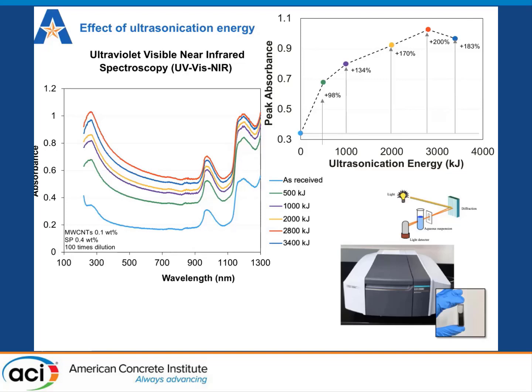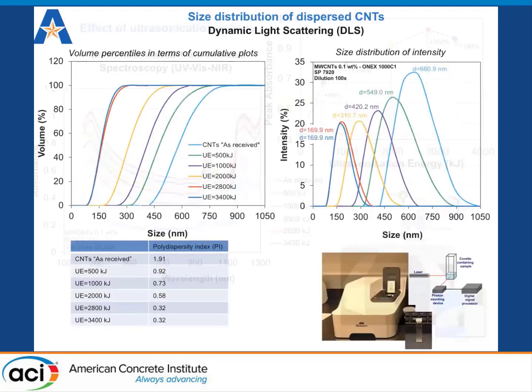What we observe is that in the beginning, even before sonication, a substantial part of the carbon is bound in large particles and does not absorb enough light. But as the energy supply increases during the usual course of ultrasonication, disentanglement occurs and a larger part of the carbon is freed to absorb more light.